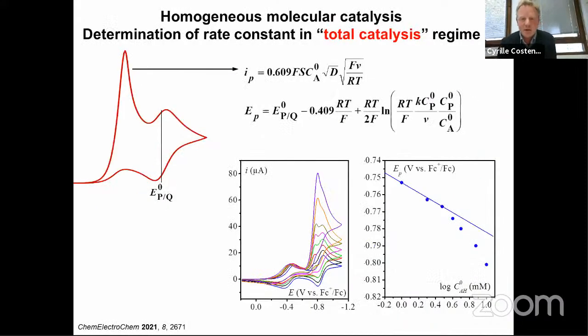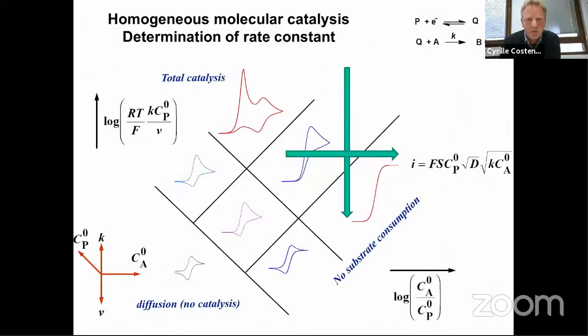There is another interesting situation. If I go back to the zone diagram, this is the total catalysis situation, where the catalysis is so fast, or the concentration of the substrate is so small, that you will consume all the substrate close to the electrode in the reaction diffusion layer, and you will get a peak-shaped CV because the CV will be controlled by diffusion of the substrate.